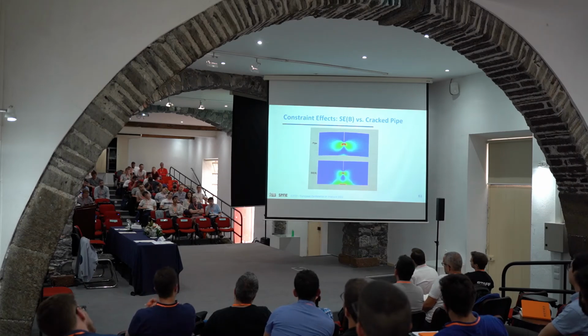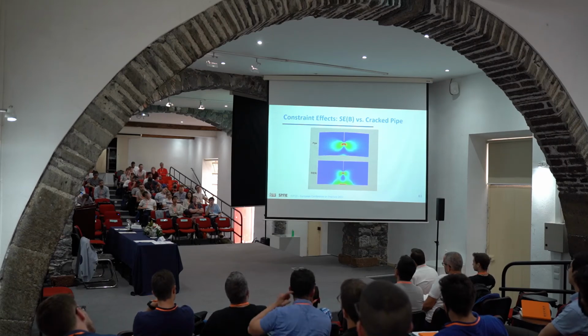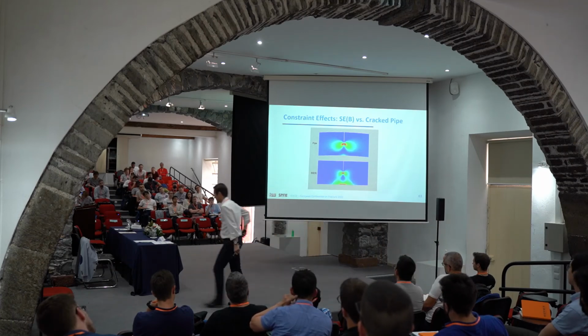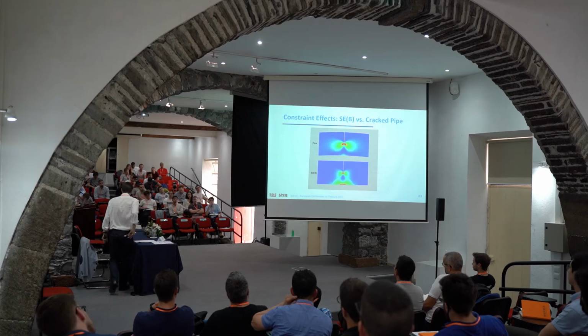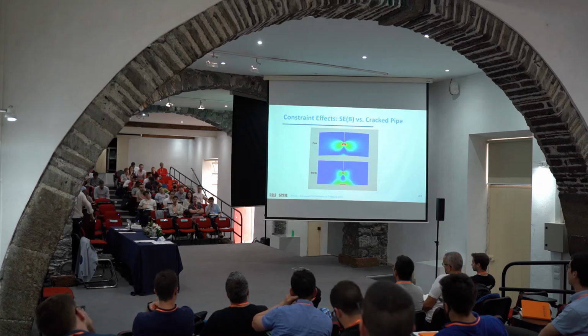And here is what I said about the plasticity. Let's hope this works. You are going to see the pipe and the SE(B). It's the 3-point bend specimen. At the beginning of load, you are going to see the red zones. The red zones are the Mises stress contours. At the beginning of load, you are going to see that it's very similar.